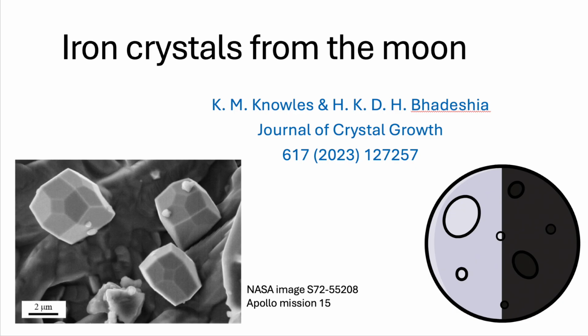Okay, let's zoom right down to the atomic level. Imagine the crystal growing layer by layer, atom by atom. Even a mathematically defined face isn't perfectly flat at the atomic scale. It has steps, like tiny terraces. Right. And at the edges of these steps, there are special spots called kink sites. These are like the prime real estate, the most energetically favorable spots for new iron atoms drifting in from the vapor to land and stick permanently.